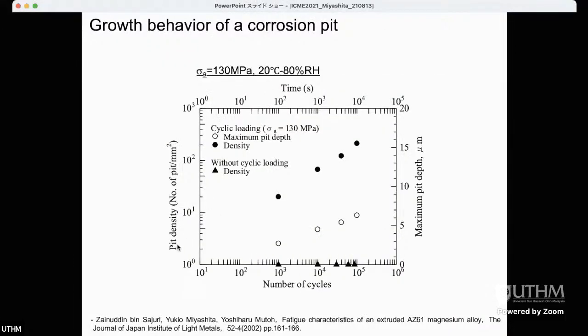And this figure shows the relation between pit density and number of cycles, or pit size and number of cycles. Size and also density of pit increase with increase in number of cycles. However, when we just keep the specimen at the high humidity condition, but without cyclic loading, we couldn't observe formation of corrosion pit. That means both mechanical loading, cyclic loading, and corrosion environment induce the corrosion pit. So this is the corrosion fatigue mechanism.